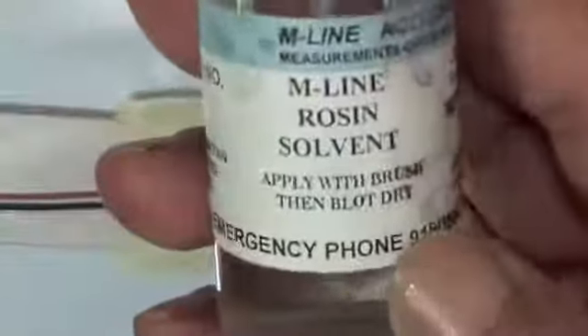And that's in fact our next step. VJ's going to use the Micromeasurements M-Line rosin solvent to remove any residual flux. This will also help soften up the paper drafting tape and allow it to come off without putting undue stress on the gauge installation. He's going to first saturate the tape and work the brush around the solder connections.